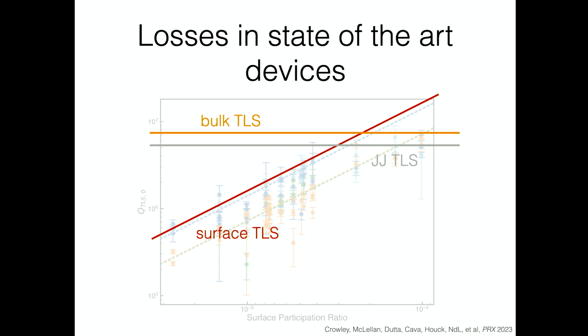I didn't show you any evidence today, but we also have some evidence that the Josephson junctions, which are made out of aluminum oxide, also have a loss contribution that is something like this. So in some ways this is very exciting because we can actually see where all these things are. It's also really, really sad because it means that if we kill one of these losses entirely, we've only increased our Qs by like a factor of 50%. So we have to solve all three problems simultaneously in order to push the state of the art.